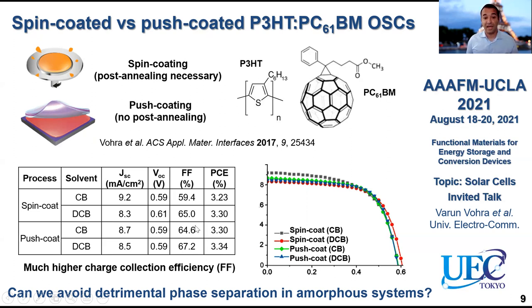Because of this higher crystallinity, you can have very high charge collection efficiency. We can also see a slight decrease in Jsc, which is most probably due to a larger phase separation, because you're giving more time to the films to form due to the slower drying dynamics. Because of this, you might generate detrimental phase separation and a slight decrease in Jsc.